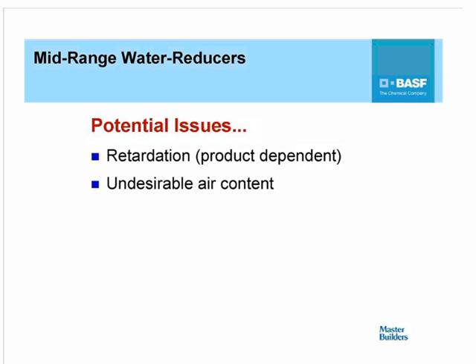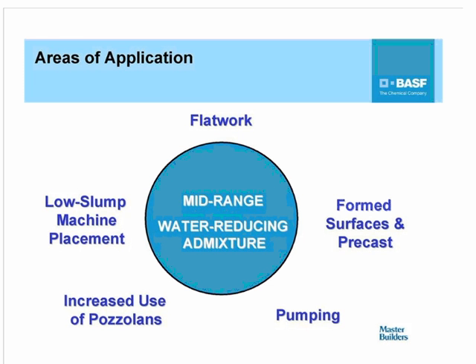However, there are some potential issues with these materials as well. Some of these issues are typically product dependent, and that includes retardation at higher dosages, as well as undesirable air contents when they're used at relatively high dosages. So these are just some issues that are typically looked out for with the use of mid-range water-reducing admixtures. But for the most part, they're used very widely within the industry in applications that range from flat work, formed surfaces and precast, pumping, low slump machine placements, as well as in areas where increased use of pozzolans occur. And this is again because of the impact that they have in reducing stickiness of concrete in the mixes.